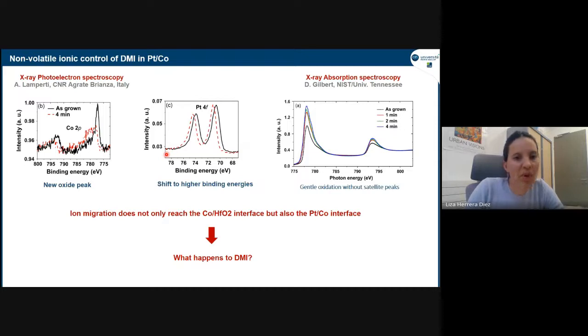So at that point, we started thinking that ion migration might not just reach the cobalt hafnium oxide interface, but it might also go further than that, which was one of the motivations of using magneto-ionics, going deeper than just the top interface. So then we thought immediately to look at DMI.